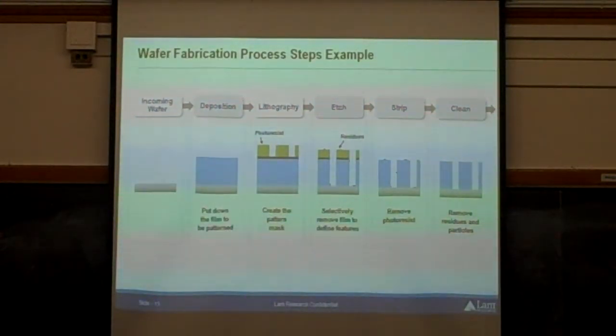And basically then I can chemically remove, I can wash away the soft parts. And I end up with this layer that's the pattern that I want, but it's in polymer. That's a material that's not going to last on a silicon wafer. So we use that in an etch process to transfer that pattern down into the underlayer, whether it's silicon dioxide or silicon nitride or a metal. And so that's the etch part.